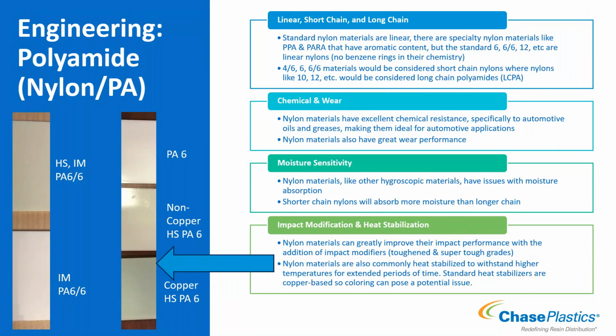So with issues of moisture absorption, your shorter chain nylons absorb more moisture than your longer chain ones do. Your 4,6, your 6, your 6,6 are more likely to have issues with moisture absorption, or maybe not being dried properly, than your long chain nylons are. So a 6,6 is going to pick up more moisture than a 12, and we have to be a little more cognizant of it when we run those materials and make sure we're drying them correctly.